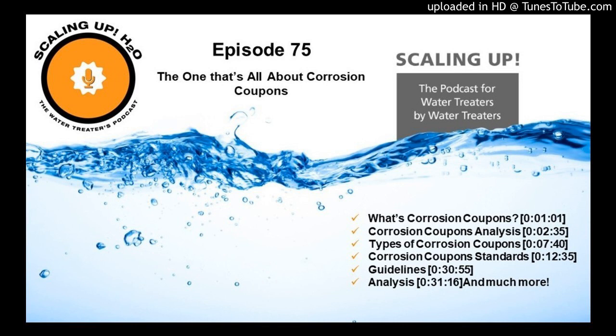Corrosion coupons are very simple. They are pre-weighed to the 10,000th of a gram. Folks, if you're wondering, that is 4 places after the decimal. So we really want to zero in on exactly what the weight is when we start. We then let that stay in the system for a certain amount of time. We're going to talk about that in a moment. And then we clean them up and then we weigh them. And then based on what the results are, we're going to change our program, or we're going to keep doing the exact same program because now we have data from the corrosion coupons.